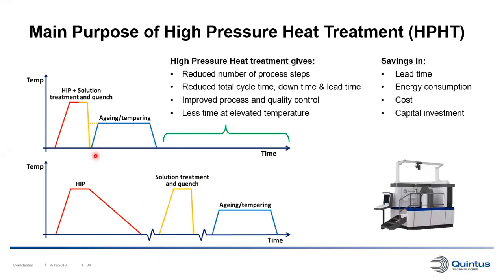And from a material standpoint, in this case, we might have a soak time in the HIP cycle of 2 hours, and then a 2-hour soak time during the solutionizing step. And of course, if we combine these two steps together, we only have 2 hours at temperature instead of 4 hours at temperature. And this can be quite important when it comes to minimizing grain growth, for example.